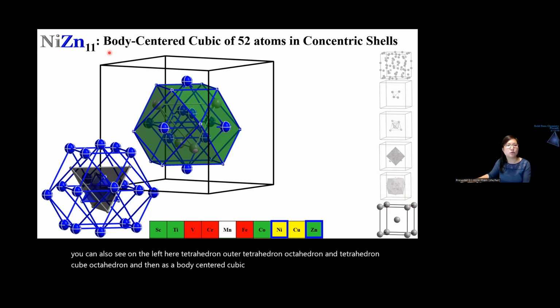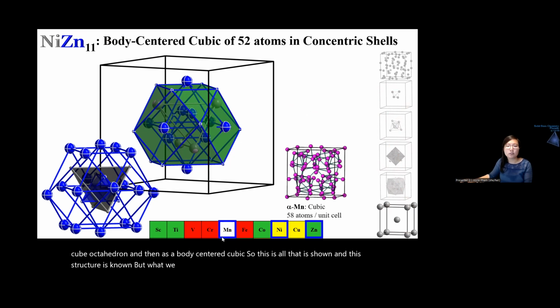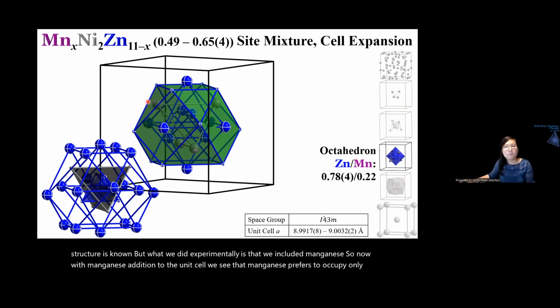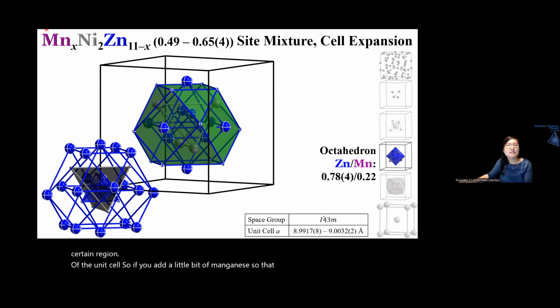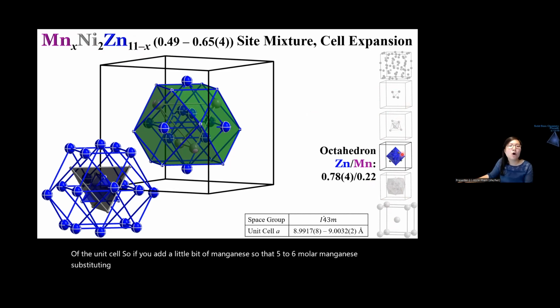So this is all that is shown. And this structure is known, but what we did experimentally is that we included manganese. So now with manganese addition to the unit cell, we see that manganese prefers to occupy only certain regions of the unit cell. So if you add a little bit of manganese, about 0.5 to 0.6 molar manganese substituting, it actually goes in only the octahedron site. So this octahedron site right here. And it will be in competition with zinc.